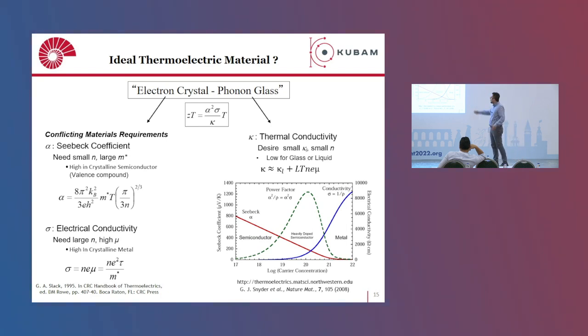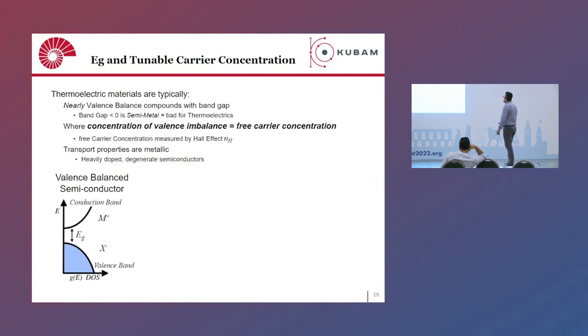So for the thermal conductivity part, you can see that this is composed of two contributions. One is the lattice thermal conductivity, another one is the electronic thermal conductivity. So this is the Wiedemann-Franz law. So the electronic portion of thermal conductivity depends also on the electronic structure of the material. Now the only thing which is actually independent of the electronic structure is the lattice thermal conductivity. So it means we have to find some materials that display good electronic properties and low thermal conductivity, and you can tune these properties either by charge carrier optimization or lowering the lattice thermal conductivity. So let me describe how we can do that.